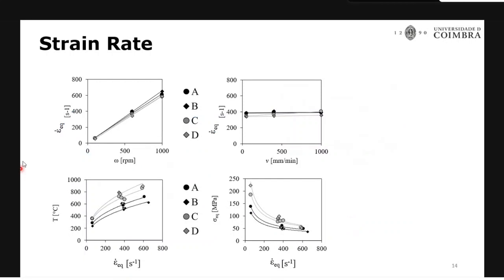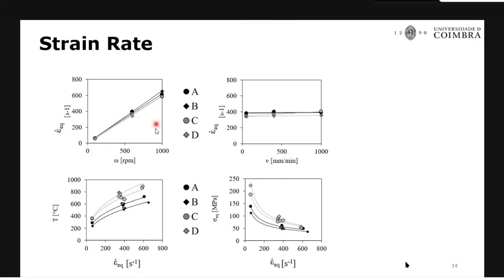Next, I'm going to check the influence of strain rate. Here you can see that as the tool rotational speed increases, the strain rate increases. So the tool rotation is highly influencing the strain rate in the material, whereas when you change the tool travel speed, you do not see such influence. With the higher strain rate, you have the higher temperature. As the strain rate increases, the temperature evolution increases. This is a very difficult phenomenon which you could not understand or study from experimental means. Only with this finite element analysis can we achieve this.